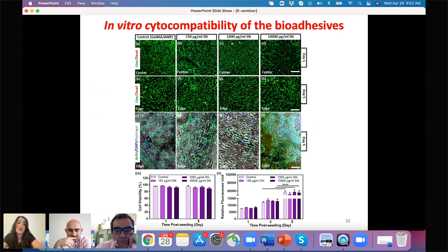In this experiment, we cultured human MSCs on these hydrogels. The control was a gel without nanoparticles with AMP, and then we introduced bioadhesive formulations with different concentrations of nanoparticles. We show that for all formulations, even the highest concentration of nanoparticles, we had high cell viability both on day 1 and also day 5. The cells could grow on the surface of this hydrogel and proliferate over time.